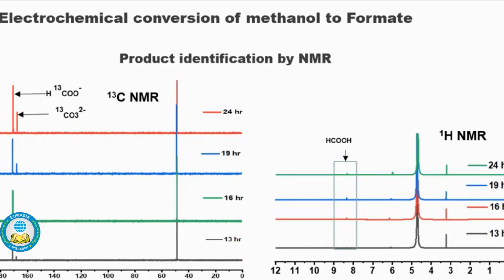For electrochemical conversion of methanol to formate, we identified the product after long-time electrolysis of 24 hours at 1.56 volts RHE, and the electrolyte was sampled and monitored with NMR at different times during the test. The carbon NMR spectra depict two chemical shifts, which are representative of formate and carbonate, and the HNMR shows the chemical shift of formate at 8.3 ppm. The formate yield increased from 13 to 19 hours, and after 19 hours it then decreased. This could be because the formate was converted into carbonate, which suppresses the further accumulation of formate, and as you can see, it is much more visible on the carbon spectra.